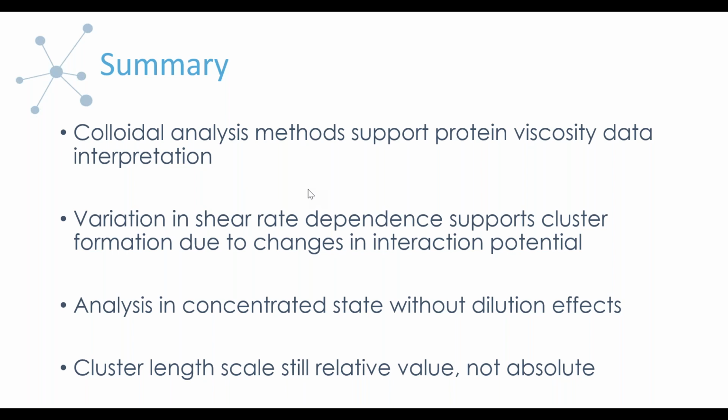Okay, so someone is asking about the difference between concentrated samples and lower concentrated proteins. All the data that we presented today was high concentrated samples at 250 mg per mil. We have started to test lower concentrations of the proteins, but we're still working through that data because there's a bit of a challenge there. You will have a change in the viscosity due to just the number of proteins that are present, and then also a change in the viscosity due to the interactions and structure formation. So we have to find a way to separate those out. Analyzing that situation is a little more complicated, but we're looking into that now.